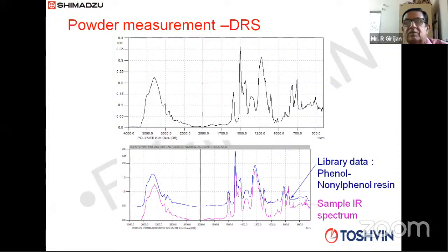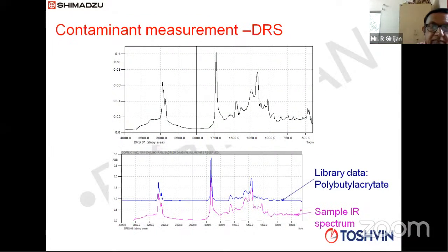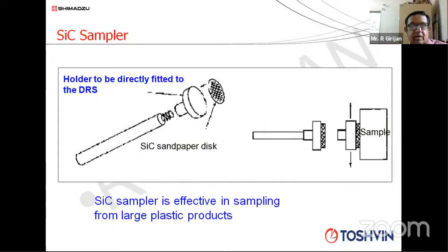Some examples: some polymeric material analyzed using the DRS attachment. And then we went for a library search. It was identified as phenol, nonyl phenol resin. There are a lot of optional libraries available for FTIR, but you have to purchase them. And this another material, polybutyl acrylate, you can identify provided you have the polymer library, which you have purchased along with the FTIR. And this is what I was talking about, SiC sampler, silicon carbide sampler, for very, very